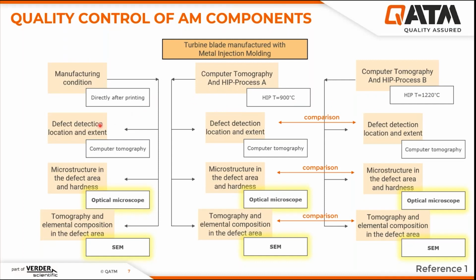Here on the left-hand side, we should have the defect detection, which means the location and extent of the defect. And then the microstructure in the defect area and hardness in the defect area. And at the end, tomography and elemental composition in the defect area. We should do this evaluation for each of these processes, and then we compare them together. The microstructure and hardness we should do on a hardness tester and optical microscope, and tomography and elemental composition should be done under a scanning electron microscope. Here is the area of interest for us. The metallographic preparation plays a very important role here.